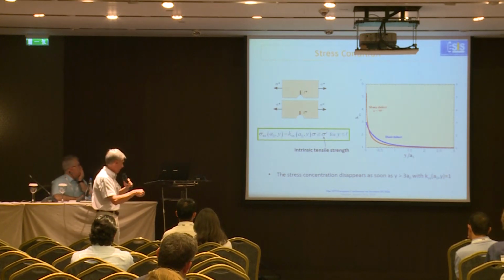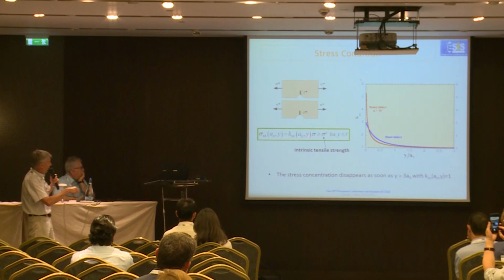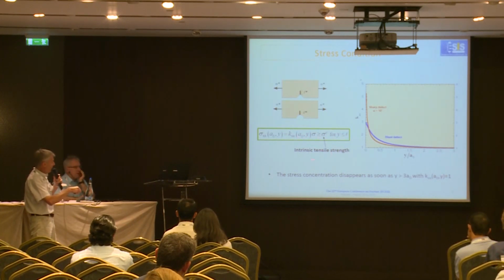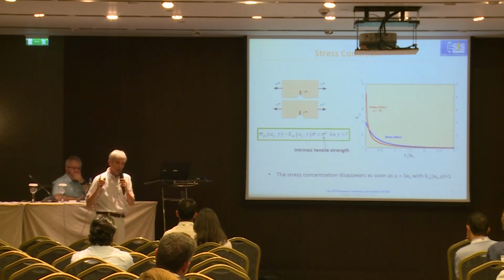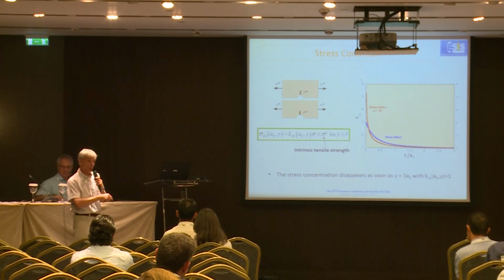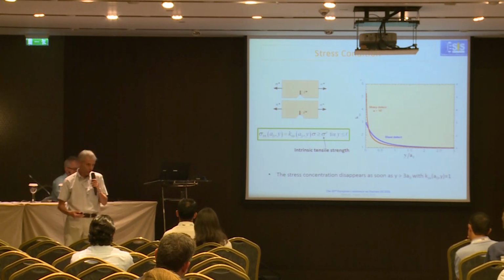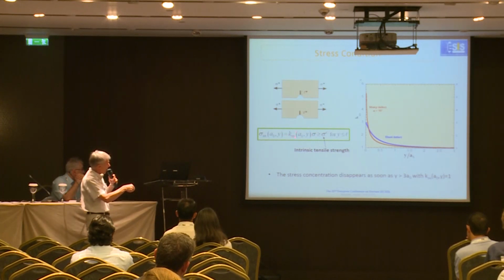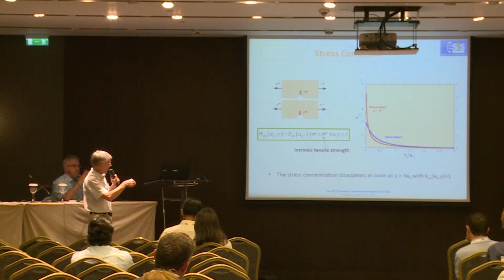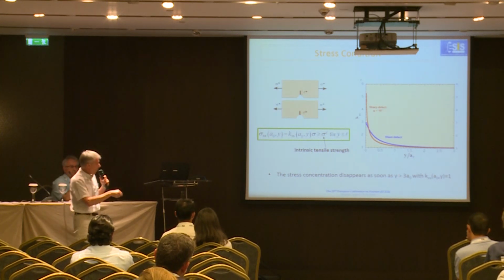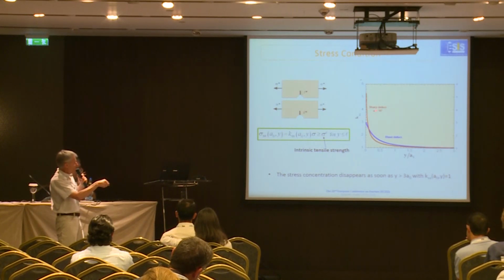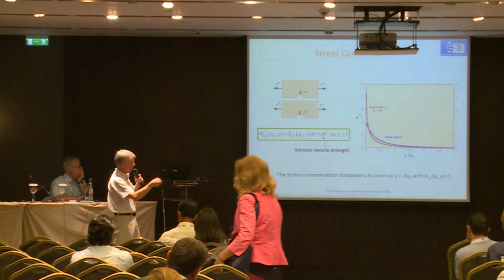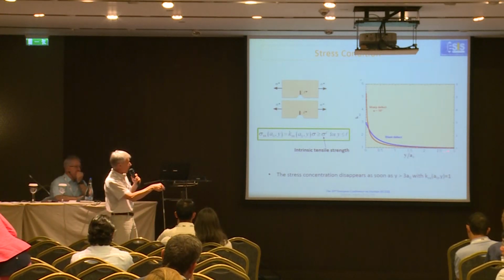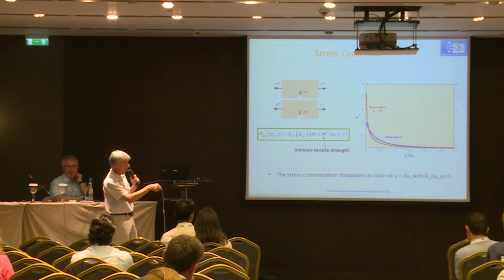For the stress concentration, we have this expression. Here is the tensile strength. Just a point: this is the intrinsic tensile strength, that is to say, the strength you obtain if you do not consider any defect in the ceramic material. The scaling coefficient K is plotted here versus the distance from the flaw tip. Of course, you have a decreasing function, and the value is higher for the sharp defect because of the stress singularity. If you move away from the flaw tip, you escape from the stress concentration, and the value of K is 1, of course.